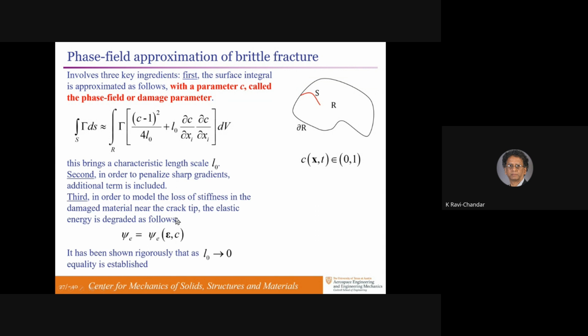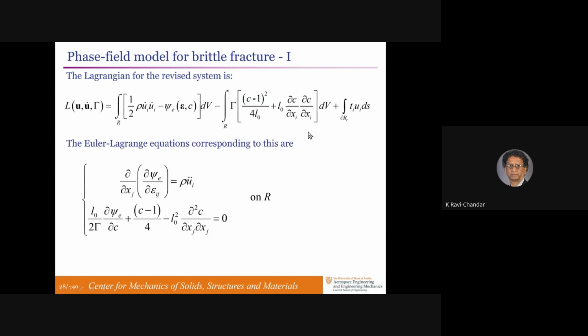Now, there are proofs that this will converge to Griffith fracture if the length scale L naught tends to 0, and there are fix-ups for fixing the fracture energy when L naught is not 0. I won't go through all of that, but the basic idea is you've replaced that surface integral by this volume integral term, and now you can write the Euler-Lagrange equations for this easily. And this is the divergence of the stress equal to the inertial term, where we have defined this thing as a new stress, damage-induced stress.